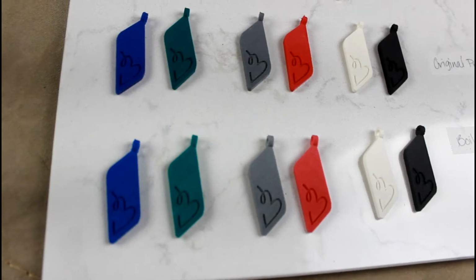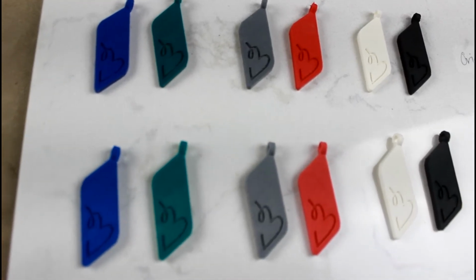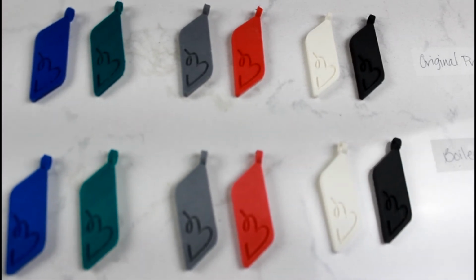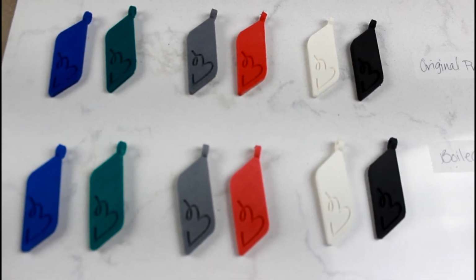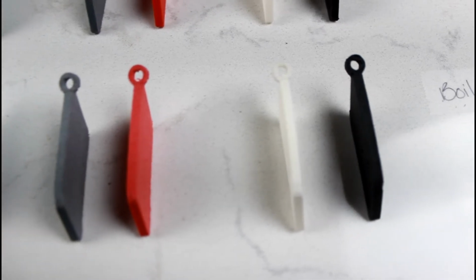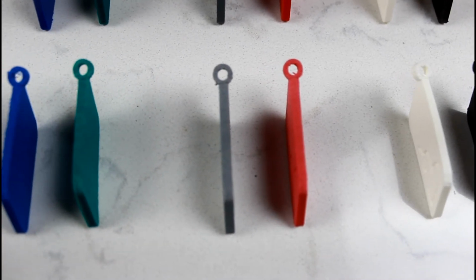Now, on other websites that I have read, it talked about doing up to 212 or 210 degrees. Throw this into a pot of boiling water and have the same effect. So I decided to test this out again with an entire set of these keychains. And again, I got warping at 10 minutes. I got warping at 7 minutes this time in the boiling one. And I had very little to no warping at the 5-minute time period.